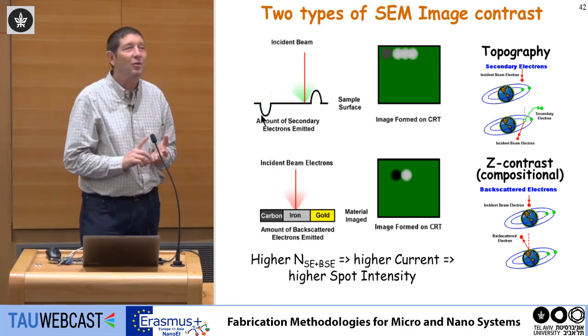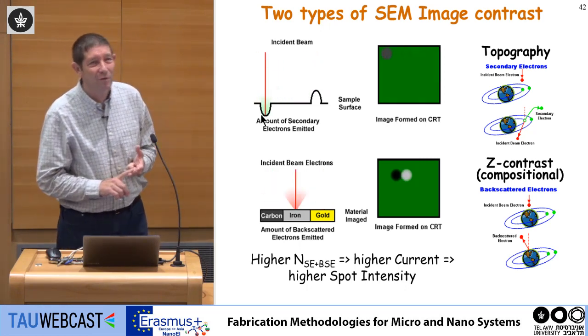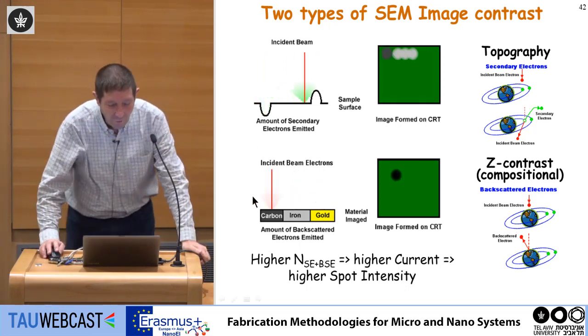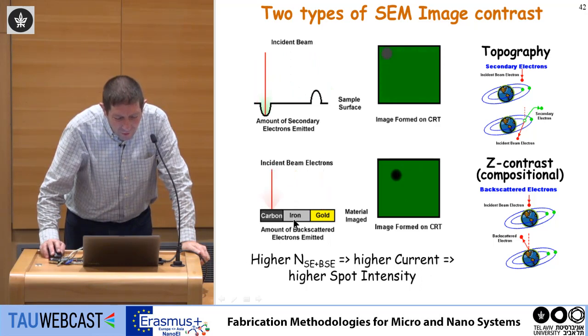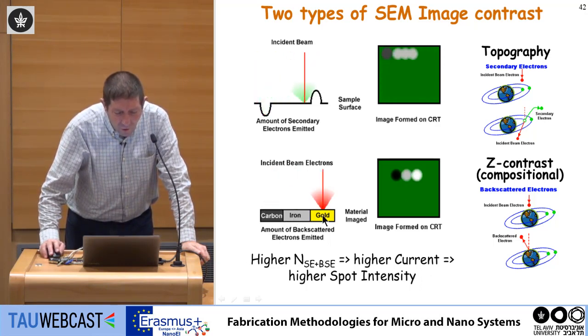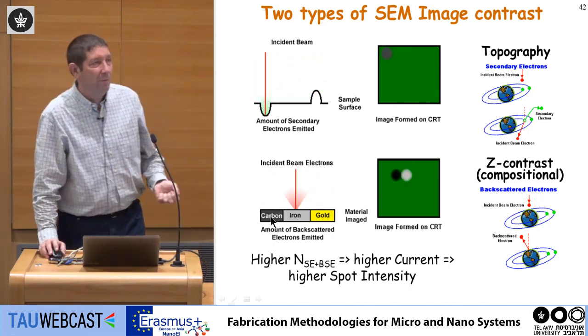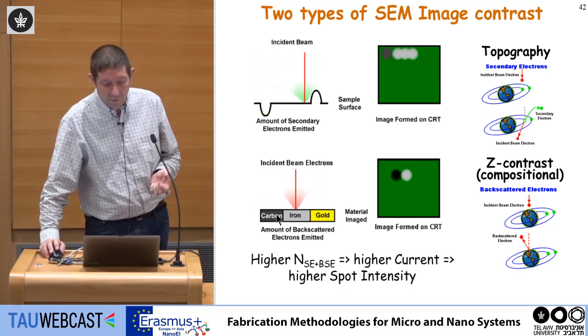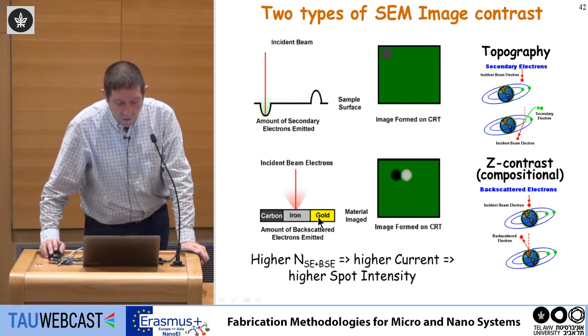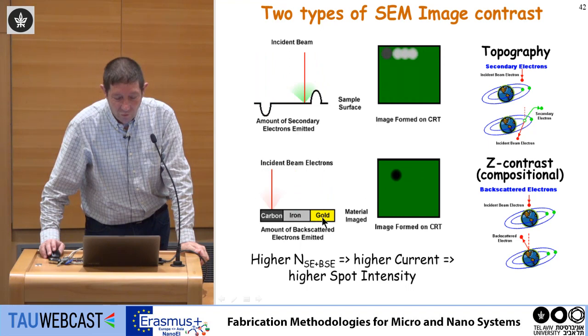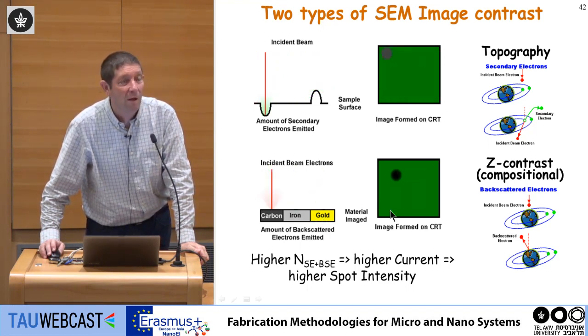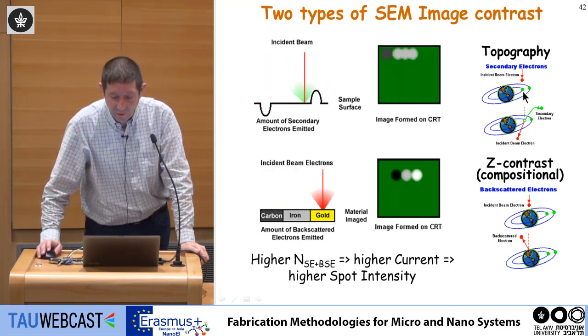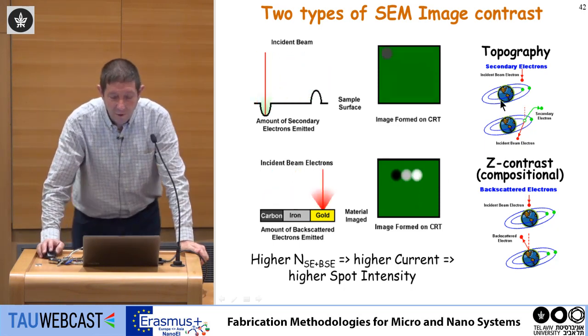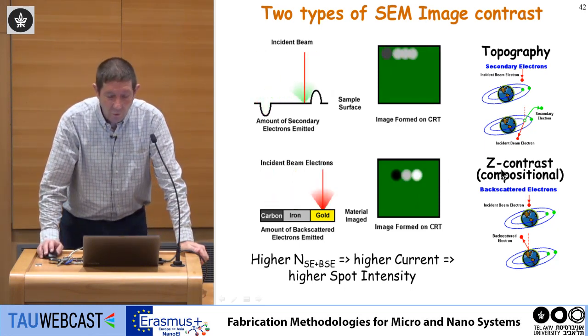So if you look at your signal, the signal depends on the mass, depends on the energy, but also depends on the topography of the surface. So if you are looking at silicon, iron, carbon, gold, carbon is a light material, not many electrons, so the signal will be weak. Iron is heavier and gold is much heavier, so gold has many more electrons, so you get many more backscattered electrons. So you have a topography contrast and also a Z contrast, compositional.